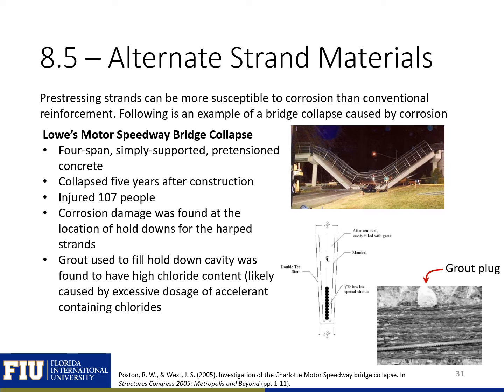Pre-stressing strands can be more susceptible to corrosion than conventional reinforcement, which is one reason we want to keep pre-stressed beams crack-free. This is illustrated by the Lowe's Motor Speedway bridge collapse, a four-span simply supported pre-tensioned concrete structure that collapsed just five years after construction, injuring about 107 people. Corrosion damage was found at the harp points, where grout used to plug the hold-down devices had high chloride content that actually accelerated corrosion of the strands, leading to failure at the points of highest flexural demand.